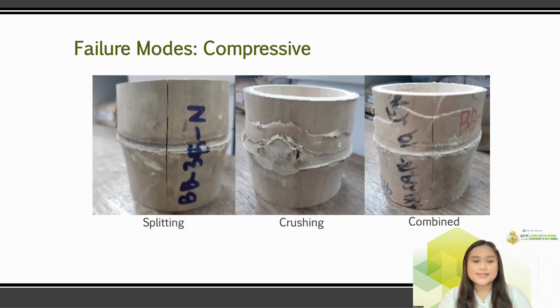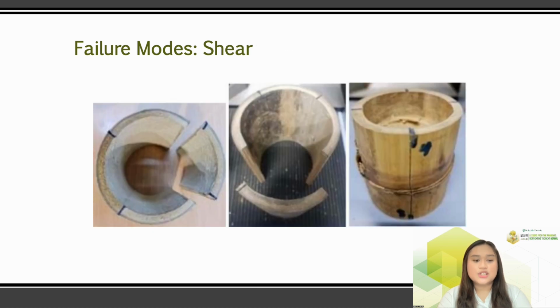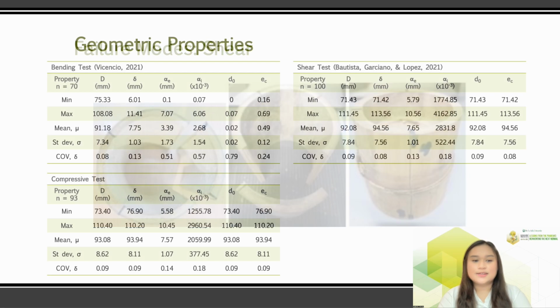For compressive tests, 3 failure modes were observed, which are splitting, crushing, and combined splitting and crushing failure. Specimens with combined splitting and crushing failure were observed to have splits occurring along the crushing zone. In terms of shear failure, the specimen failed on either 1 or 2 shear failure planes, with 64% of the total tests failed on the 1 shear failure plane and 34% failing on 2 simultaneous planes.